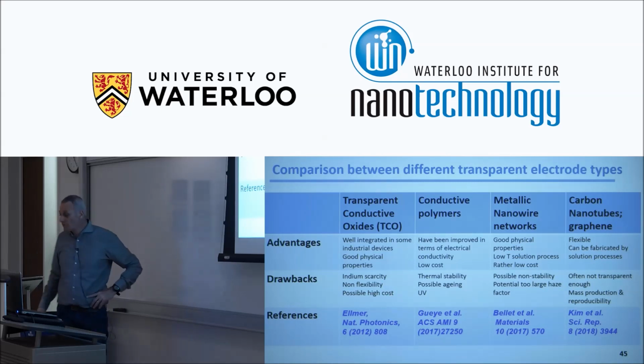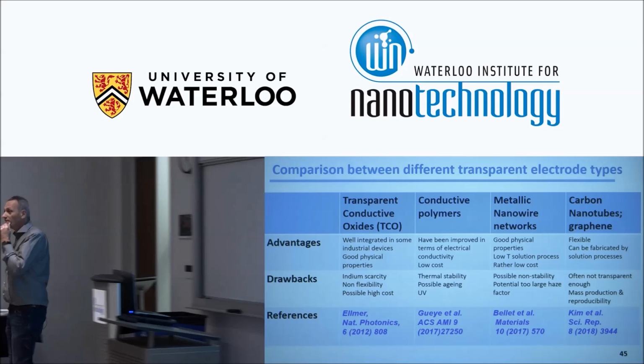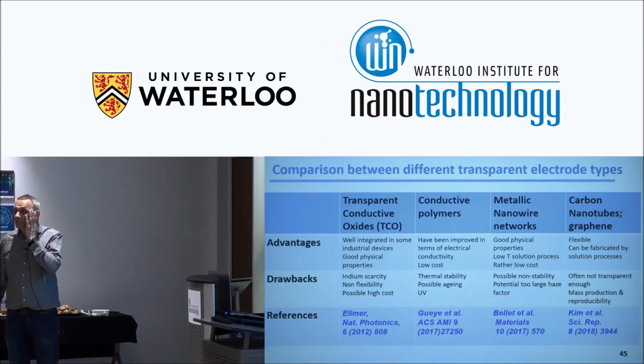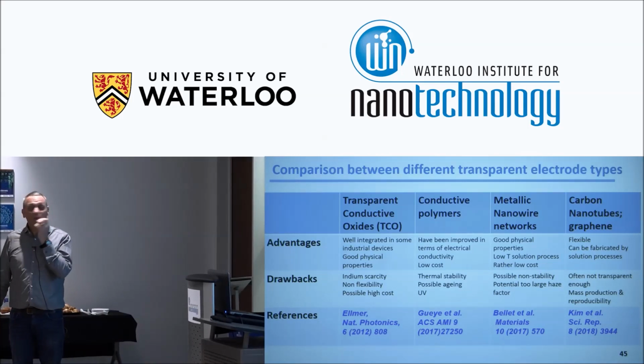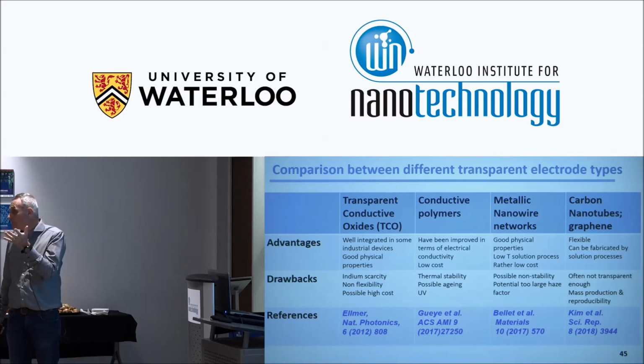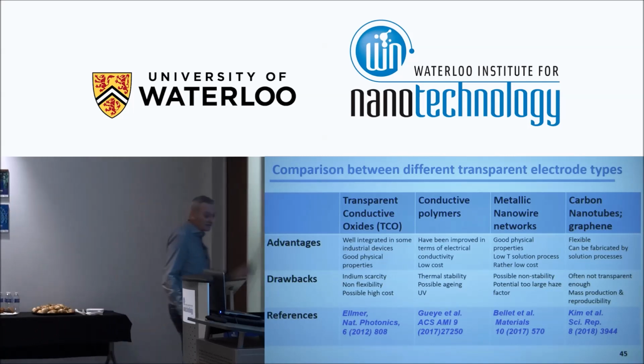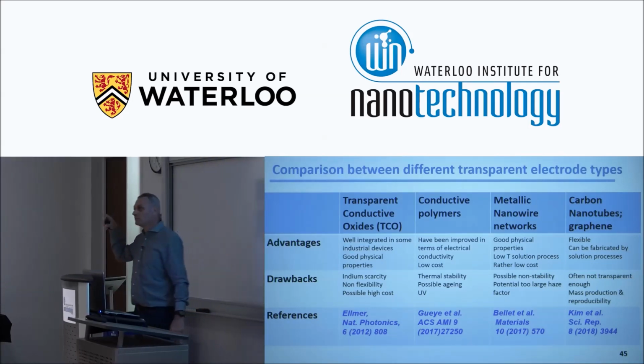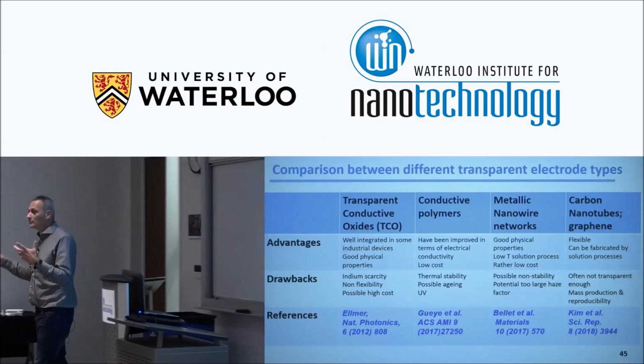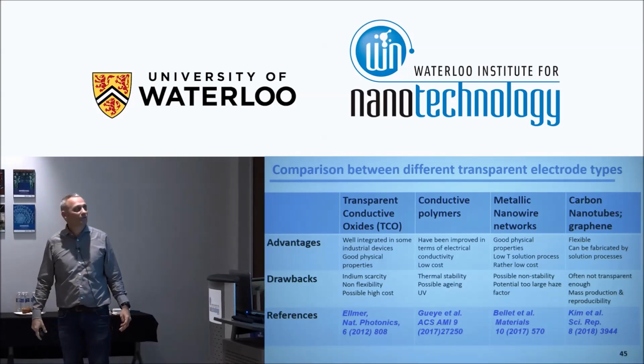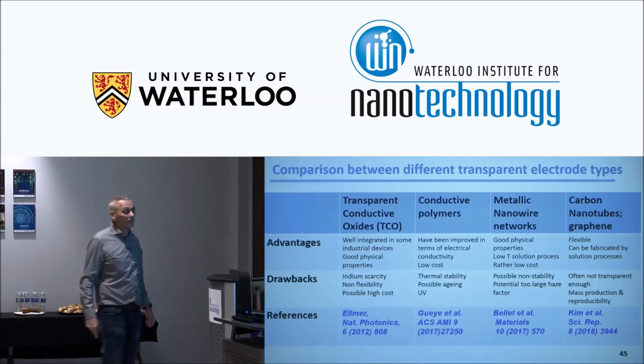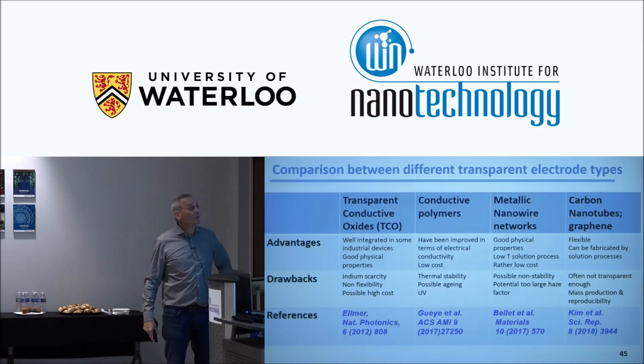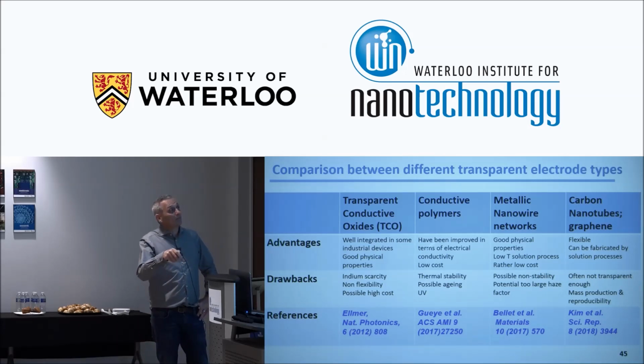Conductive polymers: I have been rather impressed by the progress that chemists have made in the last few years. Now they are starting to make conductive polymers with electrical conductivity as good as our FTO, which is the state of the art. That's very impressive, and I have a slide on that. I can't go into details because this is full chemistry, but it's based on PEDOT:PSS, though not only PSS. They try to replace the PSS with other molecules, and now they are starting to have very good electrical conductivity, with a resistivity of 2 or 3 times 10 to the minus 4 ohm centimeter. So that's very cool. They could have very good electrical conductivity and rather low cost.